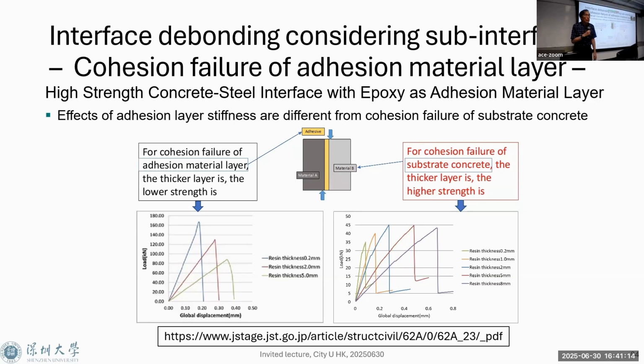Then what happens? Earlier, as I said, if the debonding happens on the substrate concrete side, a softer adhesion material layer gives you higher bonding strength. But if the debonding happens within the adhesion material layer, softer material gives you smaller bonding strength. So again, it depends on where the debonding takes place. You can get completely opposite outcomes. In this case, a soft adhesion material layer doesn't work. But in this case, if the debonding takes place in the substrate concrete, a soft adhesion material layer does work. Okay.